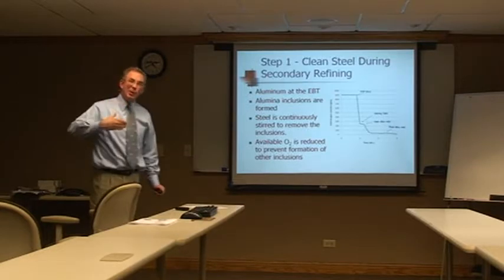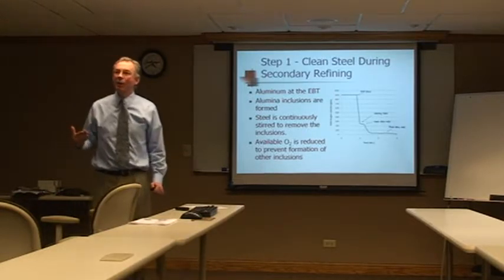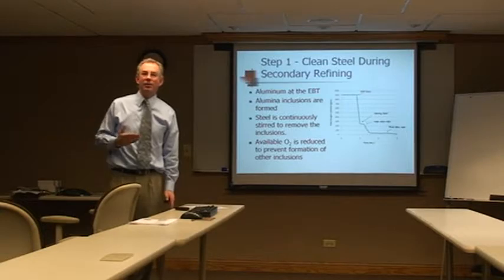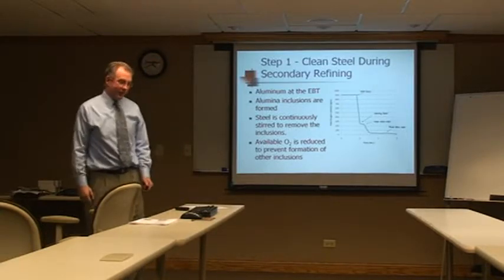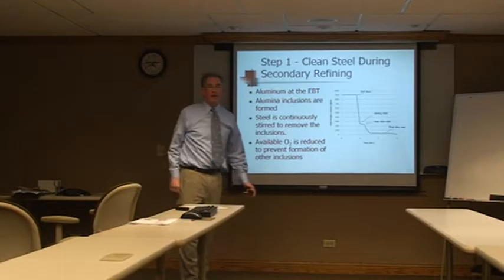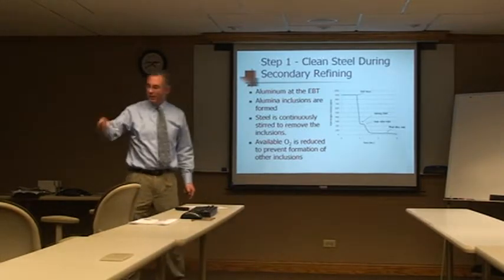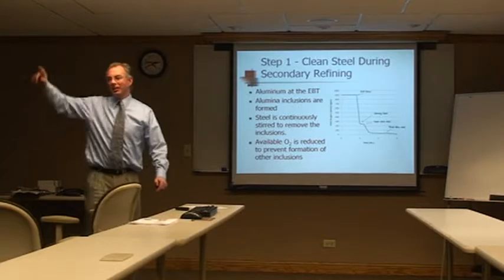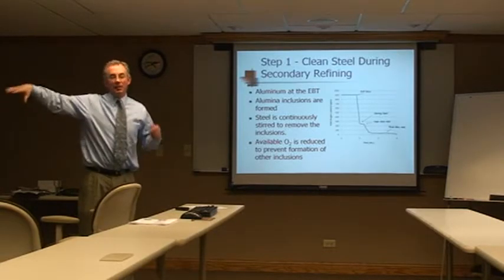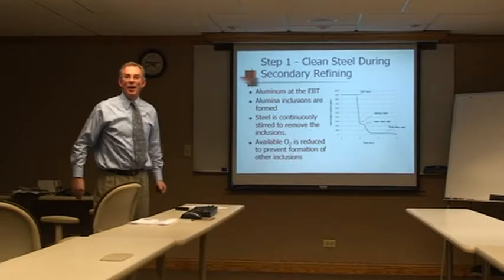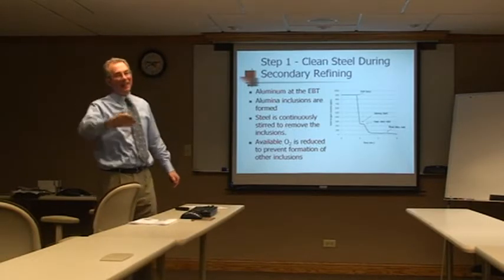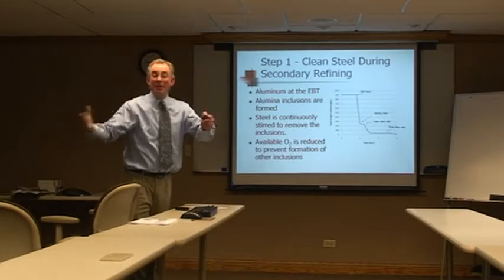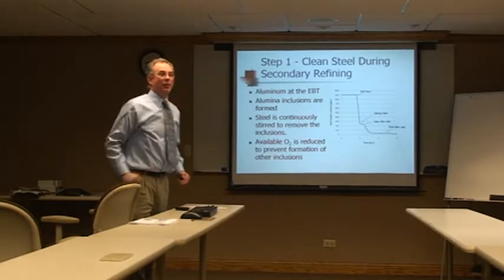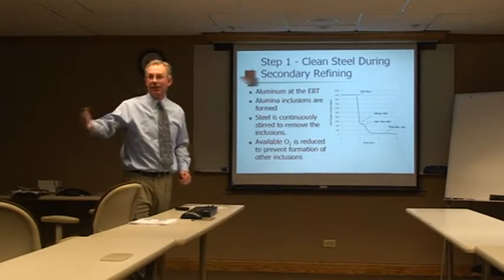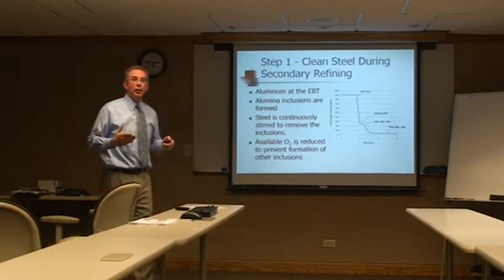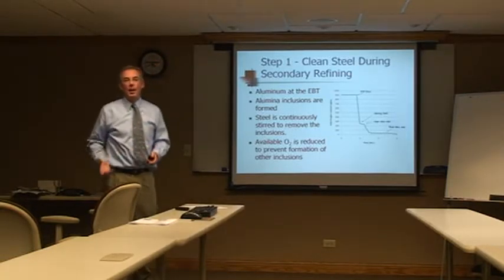Aluminum, of the commercially practical elements to use in steel making, has the highest affinity for oxygen than any other element. So if there's a molecule of oxygen there, and there's an aluminum, there's a silicon, there's a calcium. If they're all lined up, I shouldn't use calcium. The aluminum is going to go after that. Yeah, sorry, it's been a while. The Ellingham diagram. So aluminum and silicon are standing there. The aluminum is going to react and tie up with that oxygen faster than the silicon can. Okay? So by adding the aluminum, we make sure that we're going to create aluminum oxide.